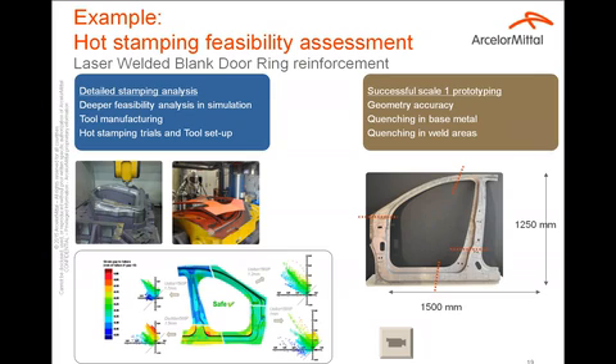So as you can see on the picture on the bottom of the slide, we have a very safe situation on all sub-blanks composing the laser welded blank after hot stamping. And then we went to a successful scale 1 prototyping phase with a very good geometry accuracy, checking, of course, the quenching in the base metal, but also in the weld areas. Here again, we will have a small video of the stamping trials performed in our press shop.